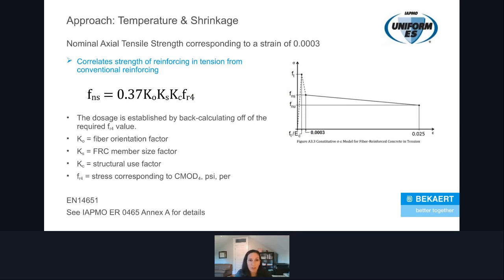And to do that, we get this equation here that nominal axial tensile strength is based on 0.37 K naught KS KC times FR4. I'm not going to go into all of the details of all of those factors, but just to say that these are basically taking into account the likelihood of positive fiber orientation in that kind of system. A slab is going to have a different type of orientation than a wall, for example. The member size factor, the structural use factor, which is essentially another safety factor if it's a true structural application. And then the FR4 is from that EN 14651 test. It's a stress corresponding to the CMOD4, that last data point in that test.